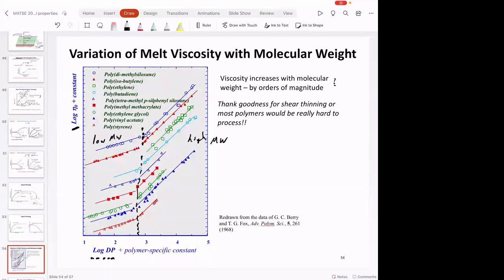And knowing what we know now, what's the difference between low molecular weight and high molecular weight in terms of entanglements? Which polymers have more entanglements? High molecular weight. And so you see the slope is higher in the high molecular weight region because you have more entanglements. And so the viscosity is going up much more quickly as you increase the molecular weight versus the low molecular weight region, where the viscosity still goes up as you increase molecular weight, but not as much because there are not as many entanglements. And you'll find out in polymer physics class that there's a key molecular weight where you start to have entanglements, and that defines the kink in this plot.